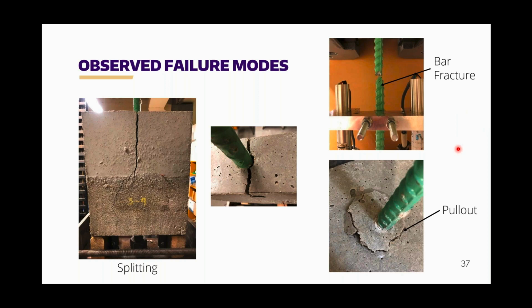Like Carolyn said, we used the results from our material properties testing to develop the experimental matrix, expecting that we would get a range of failure modes. And so that's what you see here. The majority of specimens failed through splitting, as you might expect. You can see what one of those failures looks like.